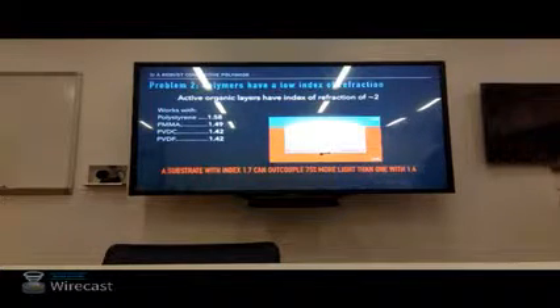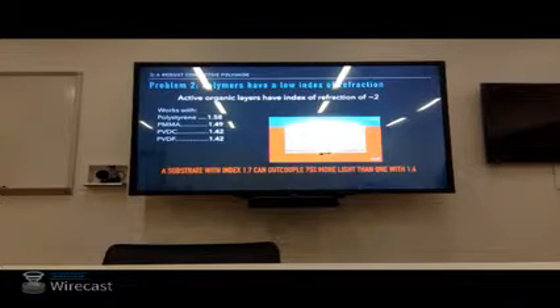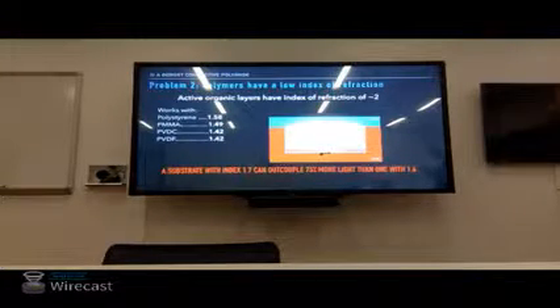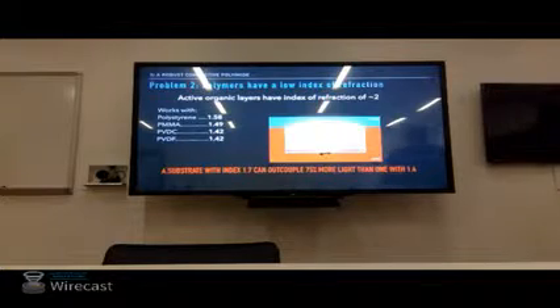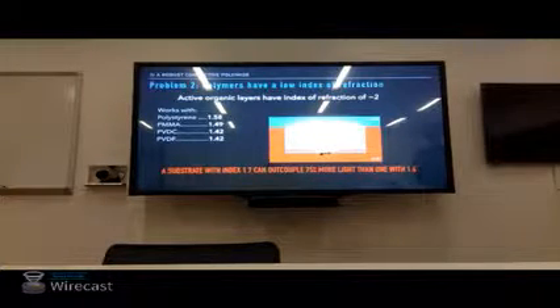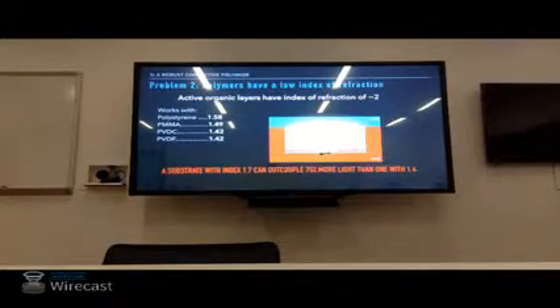Take-home point is that a refractive index of 1.7 can outcouple 75% more light than one with 1.4, and we're holding way too many things constant, so Barry might laugh at that statement, but it is true if we hold all these things constant.